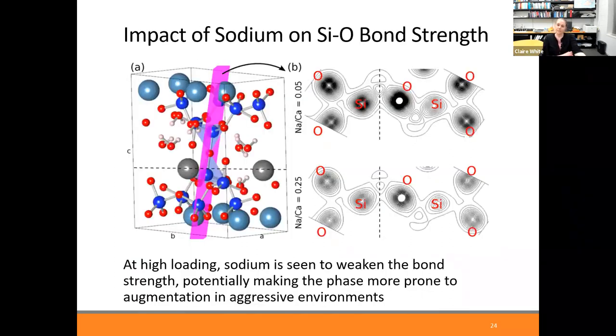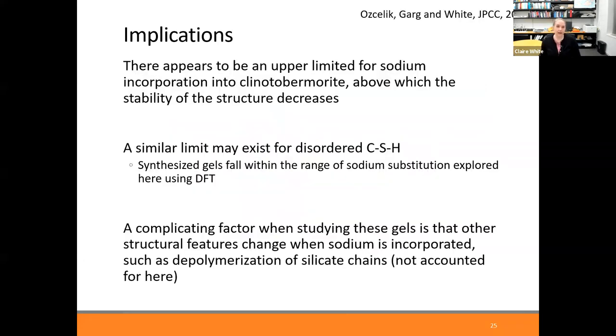We also looked at some other properties of the structure, such as the bonding strength. And what we found was that with low sodium contents, you have stronger bonding between the silicon and oxygen. As you go up to really high sodium contents, then you end up with a lot weaker bonding between the silicon and oxygen atoms. So this would make it easier for these bonds to break because they're not as strong. So the implication from these calculations is there appears to be an upper limit of sodium incorporation into this structure, above which the stability of the structure decreases. And so a similar limit to the amount of sodium may exist in the disordered CSH gel structure.